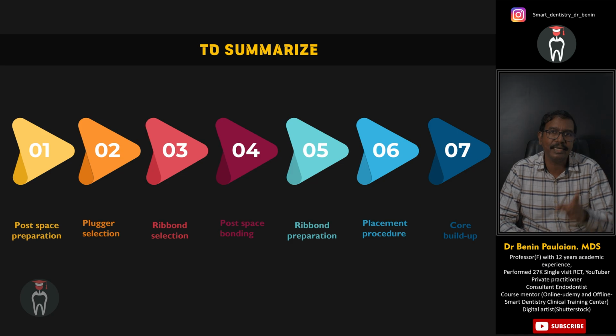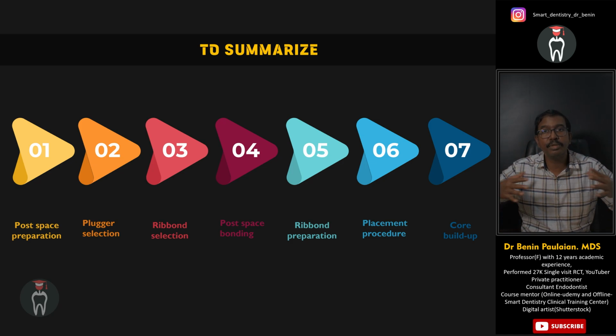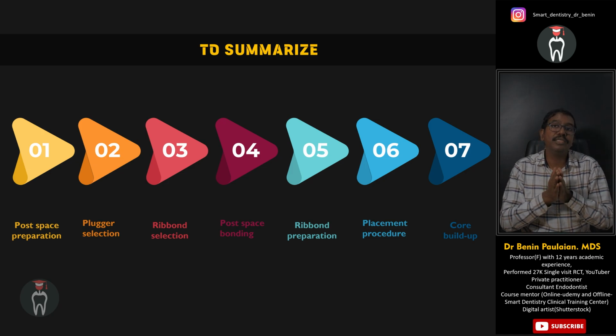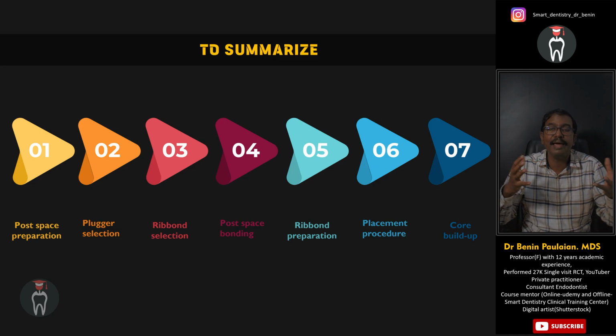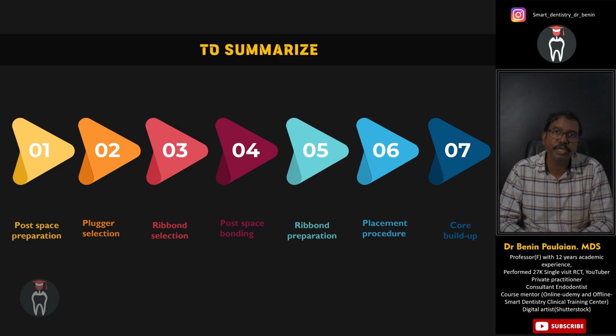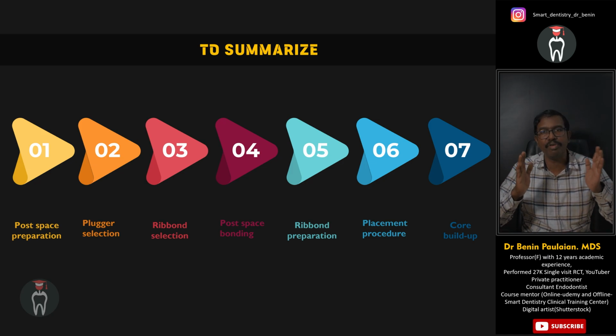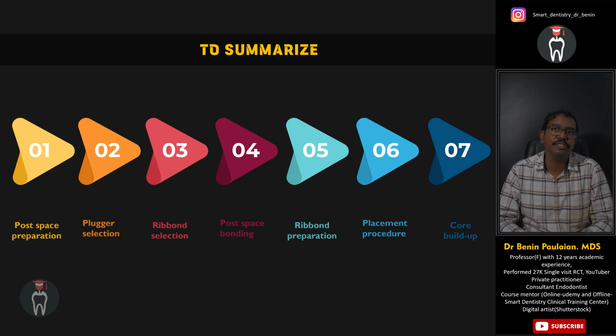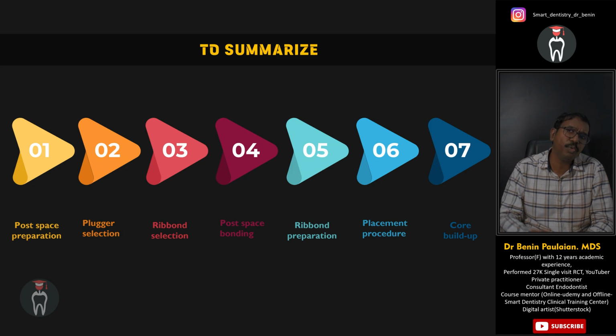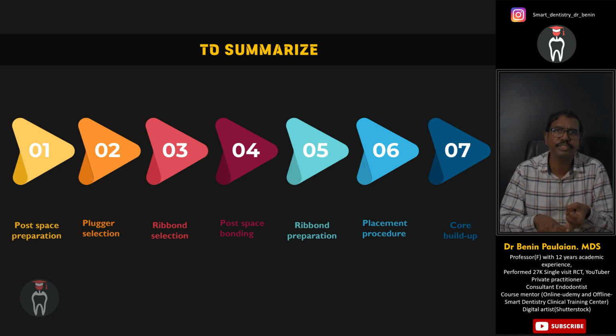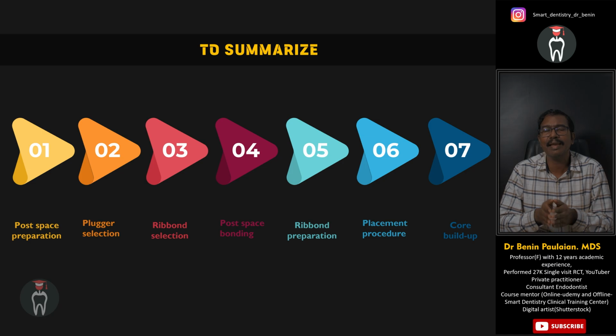The biggest advantage I would say is, one, you can change the angulation, and the second is, especially in the case of young patients, the small boys and girls with the incisors fractured and the root canal is going to be very, very wide or big, and if you are putting a post, it is going to stand in the middle like a very small one in the space, and the Ribbond can also reinforce the root. So in the case of weakened tooth structure, like an immature tooth which has undergone trauma and the root wall is very thin, the Ribbond can reinforce that also. So this is not the only application. We can use it in inlays, you can use it in large restorations, you can use it in post-endodontic restorations, you can reinforce any class 2 restorations with this material, and there are multiple uses.